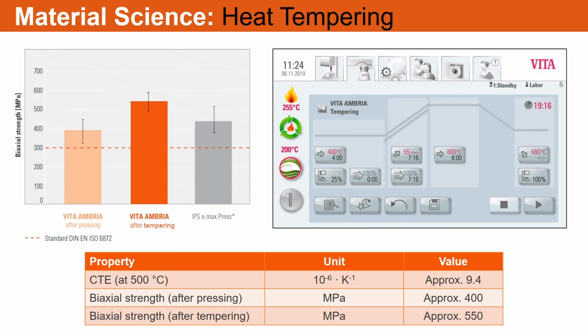And so after you've pressed it out, you can put it back in the furnace, a standard furnace, and you can increase the strength from, say, 200, the average, or 400, the average flexural strength, all the way up to a little over 500, 550. So you can actually increase the strength by doing this simple tempering firing process with the material. It's only a 20-minute cycle. It just goes to 800 degrees, holds at that temperature, and then you've increased the strength of this substantially. It jumps from about 400 all the way up to about 550,